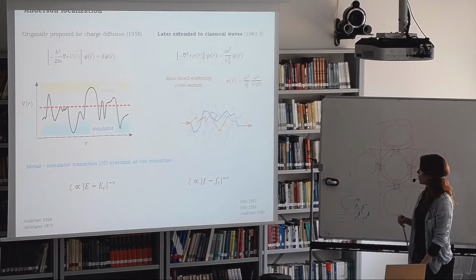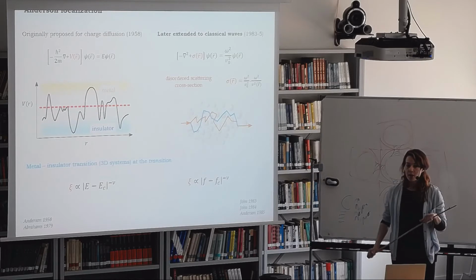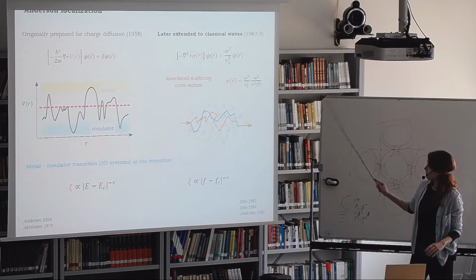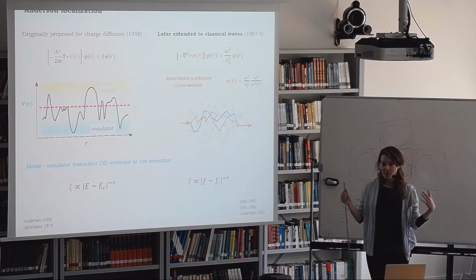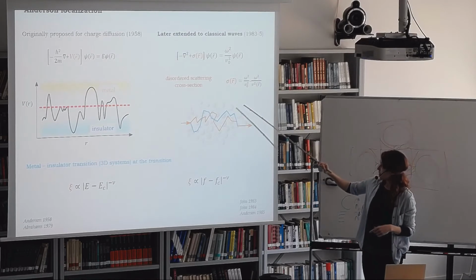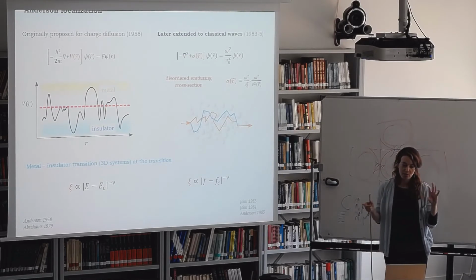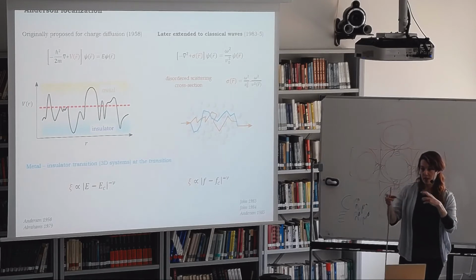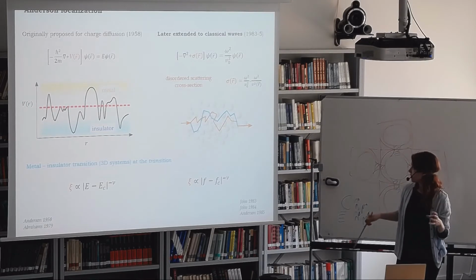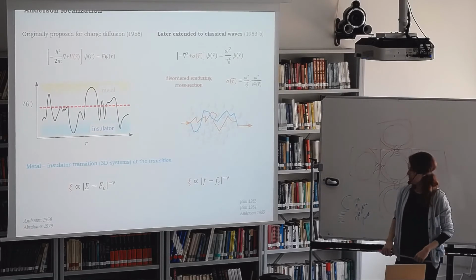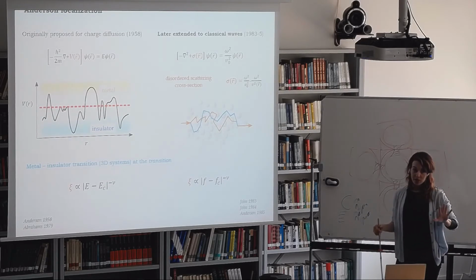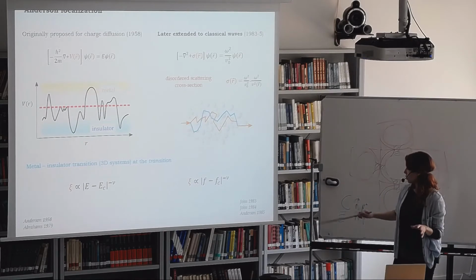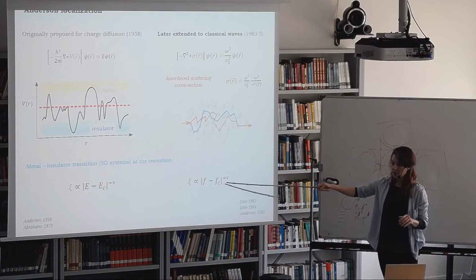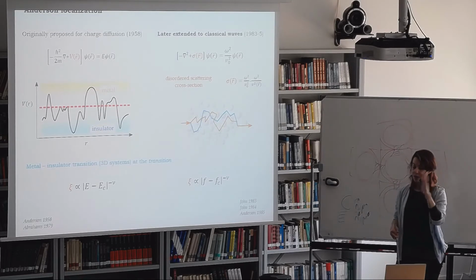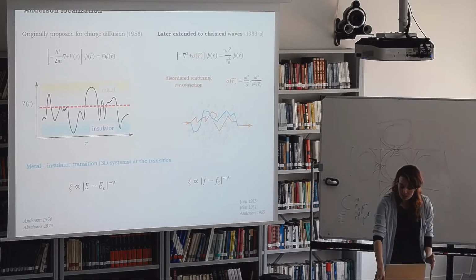So then the theory was later extended to classical waves. The main difference here is that we have a slightly different wave equation. Here the disorder comes in, not in energies of the lattice sites, but in the disordered scattering cross-section. So for instance, if you have our sample of beads, the disorder is in the positions of the different scatterers. So again, in 3D, you have a phase transition between conventional diffusion and the localization regime, which is governed, for instance, by changing frequency. So that's what you were doing before. We changed the frequency, and then we went into a different regime.